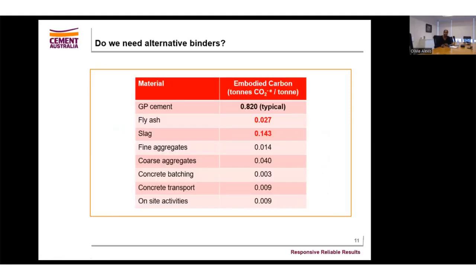So if we look specifically at numbers, GP cement, when it comes to embodied carbon or CO2 emitted per ton, is approximately, and this is just a generic number, 0.820. When looking at fly ash and slag, fly ash is 0.027 and slag is 0.143. So they are significantly low when compared to GP cement. And this was the reason why fly ash and slag were introduced into concrete, to really reduce this number here, which is the GP cement content. However, when we no longer have fly ash and slag, we'll need other substitutes that will ensure that this GP component of 0.82 remains low in concrete.